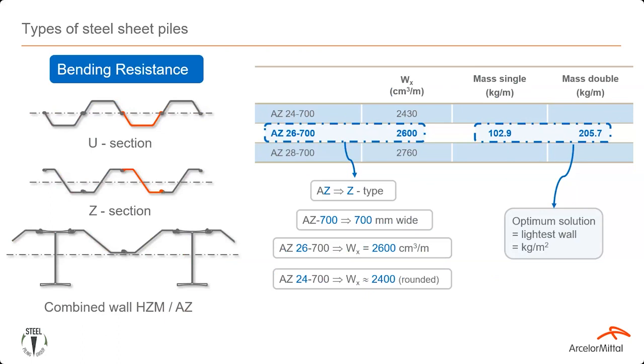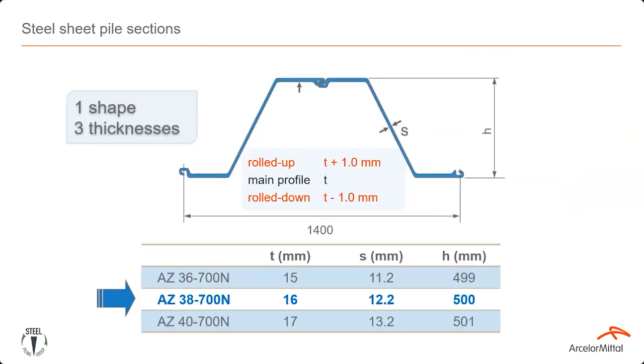And the piles, they are named simply based on the shape. If you look at our general catalog, we'll have 4 different pages to give you the sheet pile sections. So there's quite a lot to choose from. And if you look at one of the piles itself, let's say, for example, an AZ 26-700, A is for ArcelorMittal, Z is the shape, 26 is actually the key number here. It just means it's a section modulus, which is usually rounded to the nearest 100. And they also give you an indication of the strength of the pile.